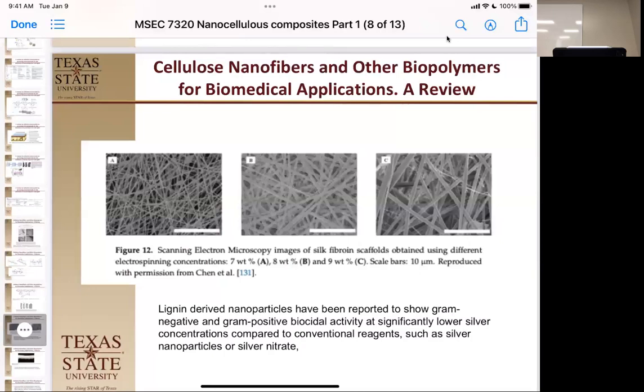So then they figured out that when they processed these things and added to them some lignin-derived nanoparticles, not nanocrystalline lignin, by the way, because it wasn't fully crystalline, they showed that they could have gram-positive and gram-negative bioactivity at significantly lower silver concentrations than conventional agents. So what they did was they took the great thing about silver being a great antibacterial agent, and instead of having to have a large mass of the silver, they put this activated surface on here and put a lower dose of silver in it that had an even better activity.